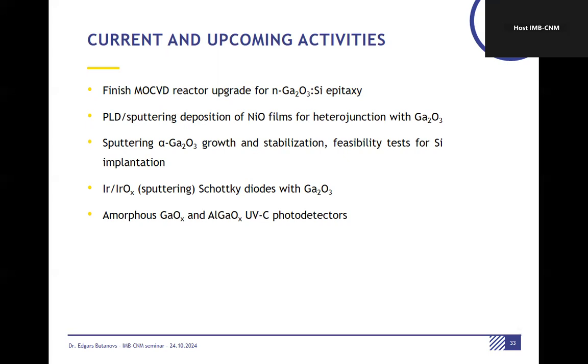It's more of a technological process for real commercial devices. Amorphous gallium oxide and aluminum gallium oxide are promising for UVC detection, mainly because the process is cheap. You can do large scale and you can get decent quality detection. So we are pursuing that as well.